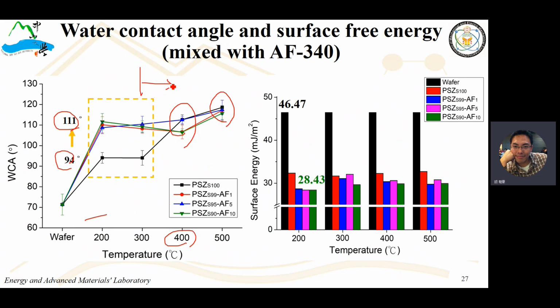Then we calculate the surface energy. We figure out that the surface energy of the silicon wafer is about 46.47 millijoule per meter square. And we spin coated this fluorinated compound. We find out the lowest surface energy is 28.43 when the cross-linking temperature is 200 Celsius.